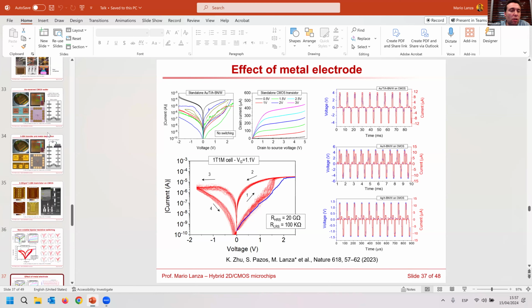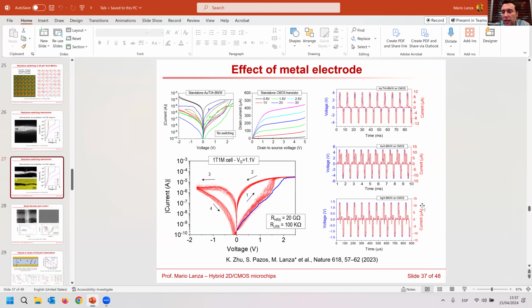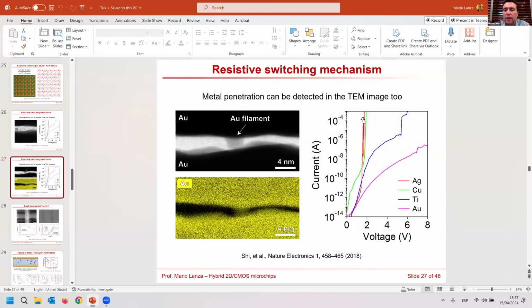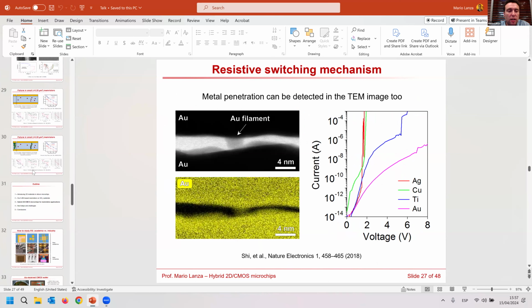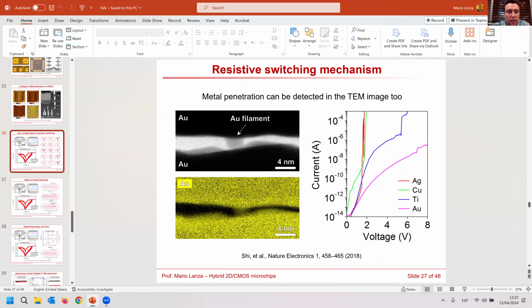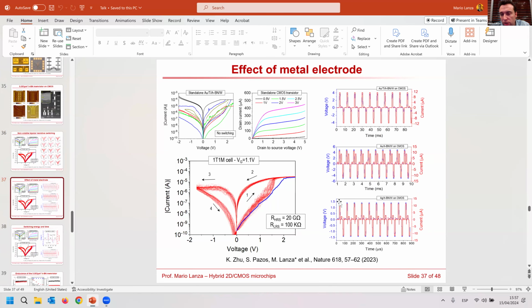Yeah, we have tried in all cases. We have tried in the very early stage. We see with the silver, it switches very, very quickly. And the same happened here. With the silver here, it switches at much lower voltages. This is related to the much higher diffusivity of silver. That is something known very well.